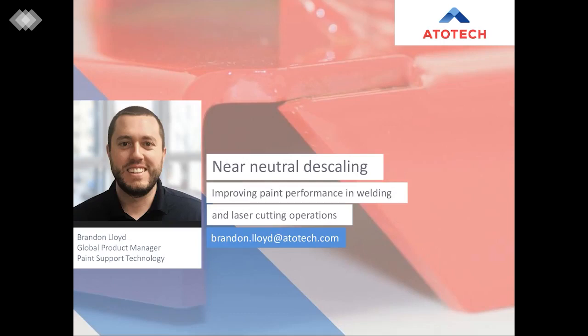Yeah, absolutely. So as we saw in the slides, and what was exhibited with the auto deposition copper evaluations, this concept, obviously, we utilize it to mimic how a paint would adhere to it. But the same is true for the plated metal. And these organic scales react similarly for the adhesion of plated metals versus paint. So these scales still prohibit the metal from plating to the part and fully covering the area. And this can result in poor performance, whether it's for functional plating or decorative plating. And we certainly have a few applications globally that have integrated these products in plating applications as well.